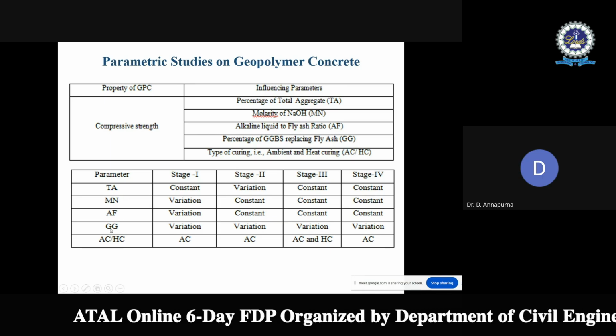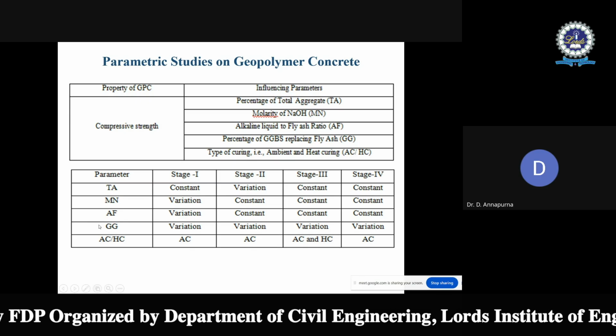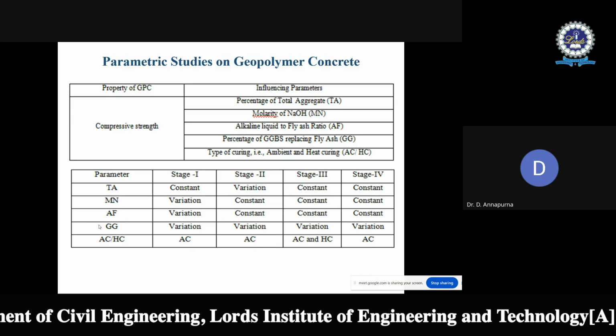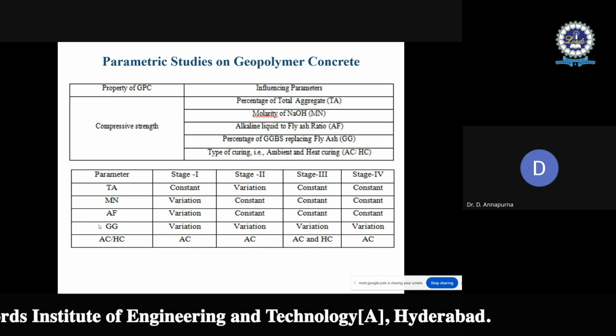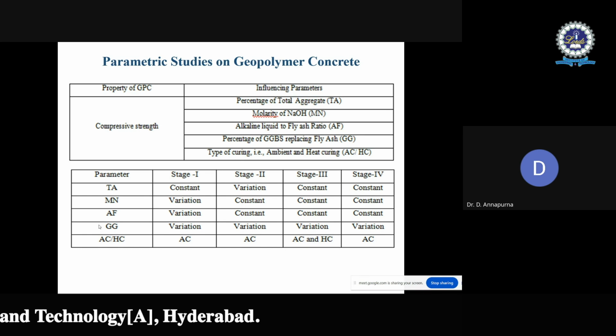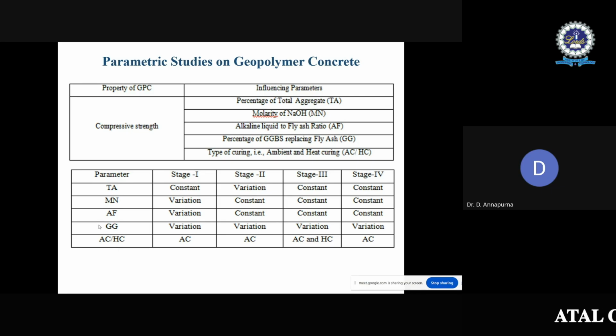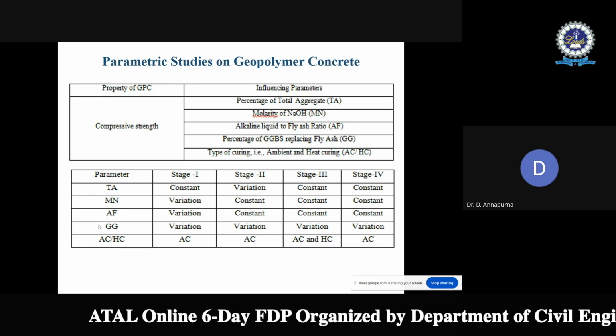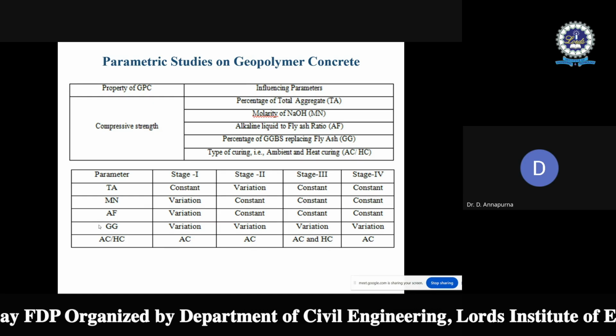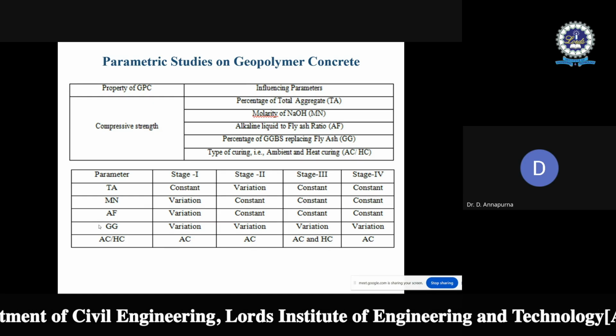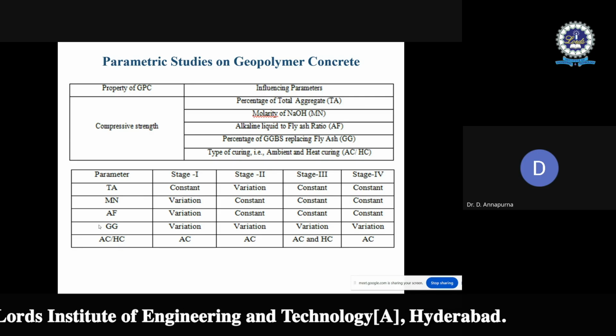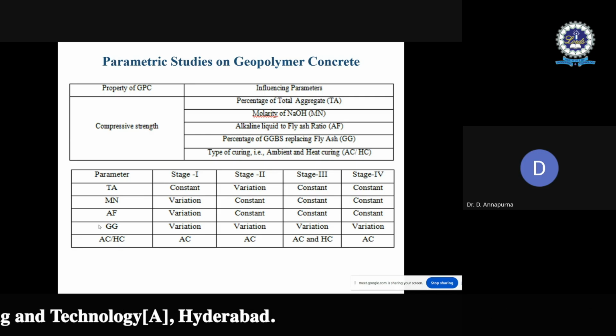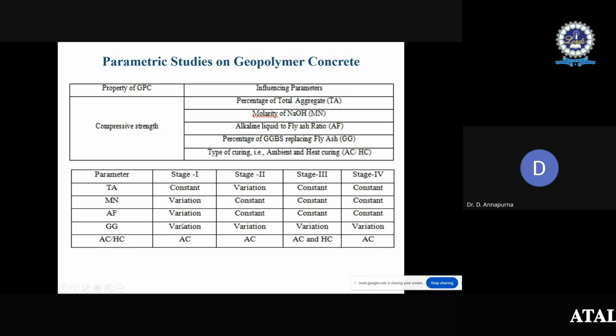Then comes the GGBS variation. As already mentioned, fly ash takes a longer time to set to form the geopolymerization product. And to enhance that setting action, to shorten the setting time, GGBS is added because it is rich in calcium oxide. The percentage replacement of GGBS considered here is 10 to 50 percent: 10, 20, 30, 40, 50 percent. So this variation is also considered in the stage 1 parametric variation.